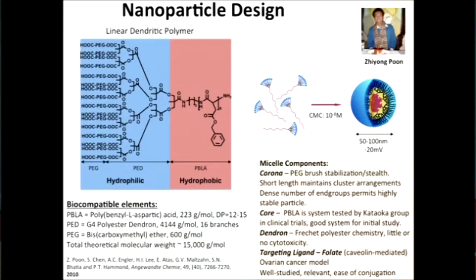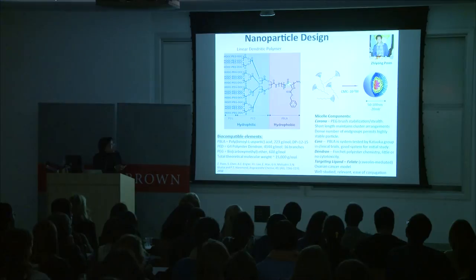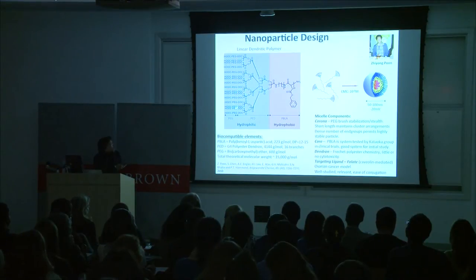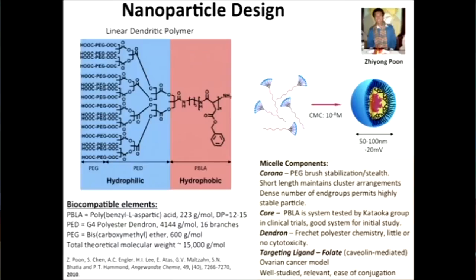So this is the structure of this nanoparticle system in which we have a polybenzyl L-aspartate block. It's a polypeptide repeat here, with a protected acid group here with this benzyl group. And the second block is actually this polyester dendrimer. It can hydrolyze very readily through the ester linkages, which makes it a fairly biocompatible system. So we have a polypeptide, which is reasonably compatible, and we have this polyester, also quite compatible. And to this, we've attached PEG, which is polyethylene glycol, also known to be compatible. We use the free acid groups we've attached here to essentially do chemistry in which we attach the folic acid group. There are 16 end groups on each of the dendrimers. So this is what the system looks like.